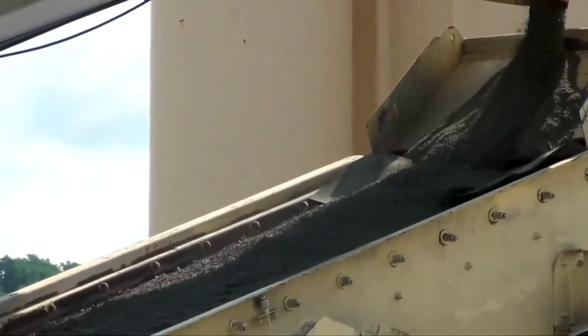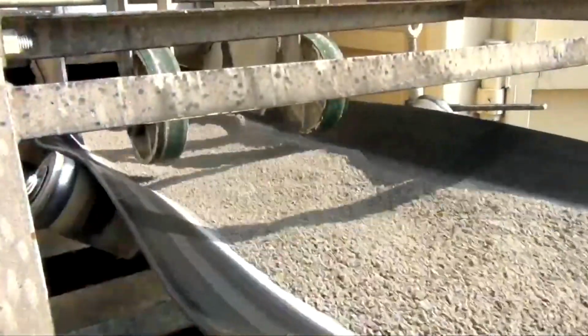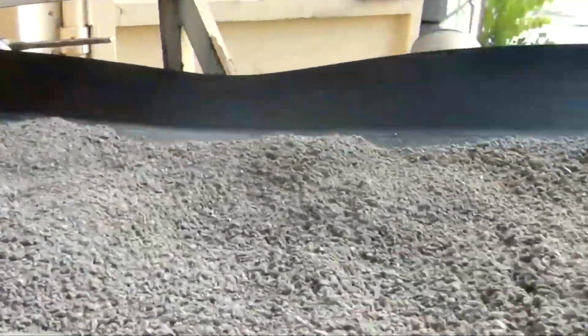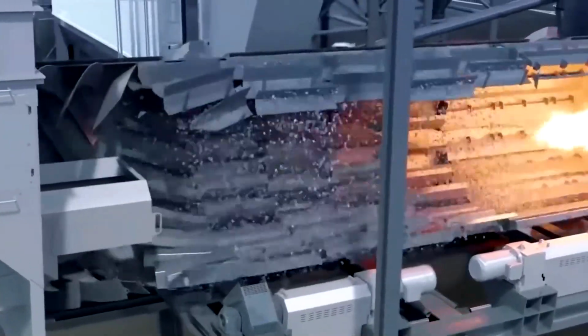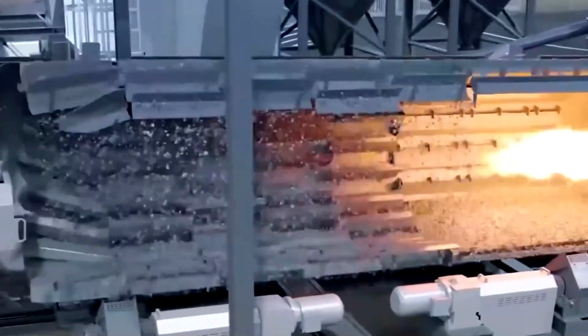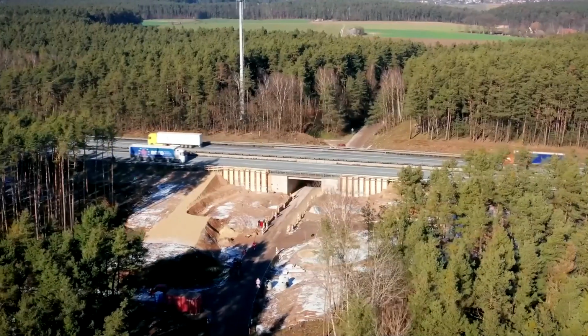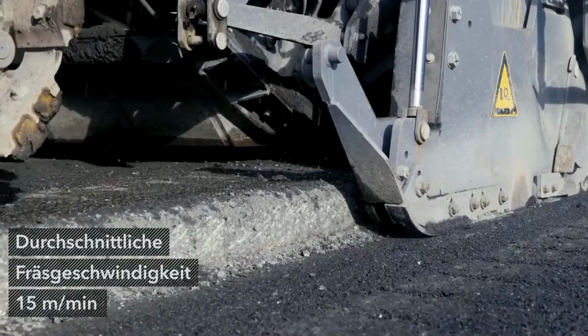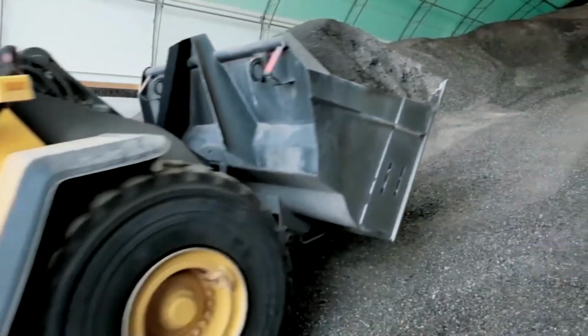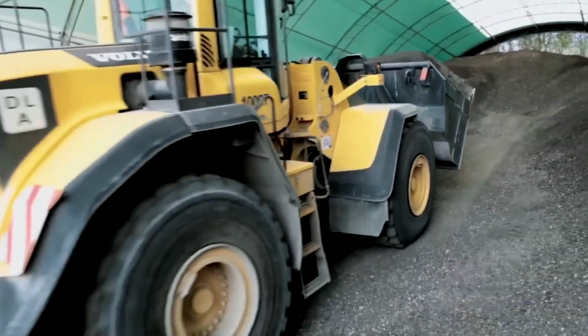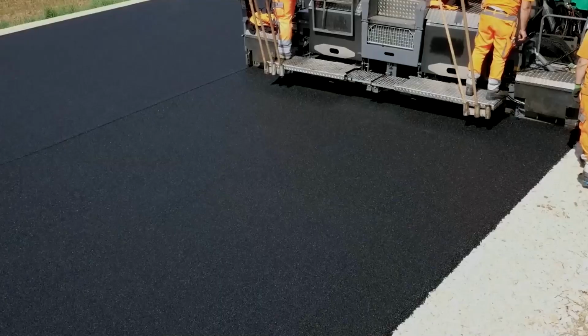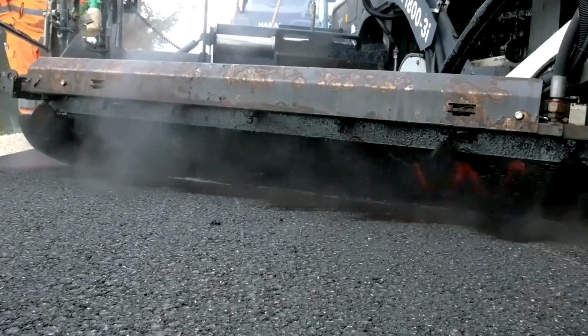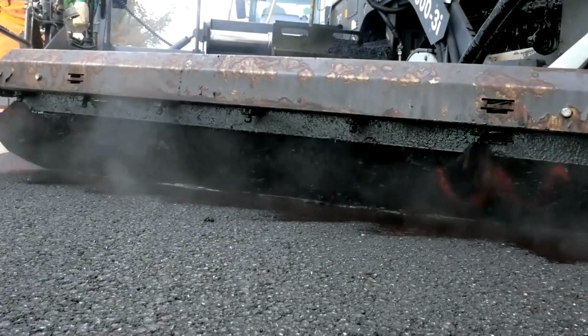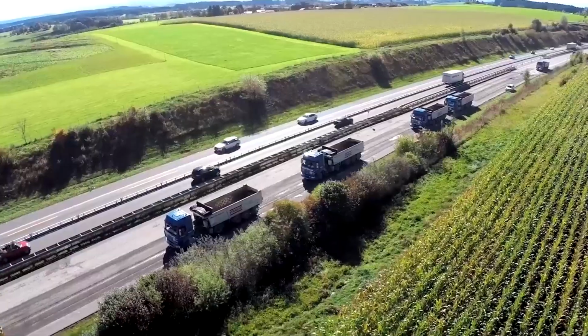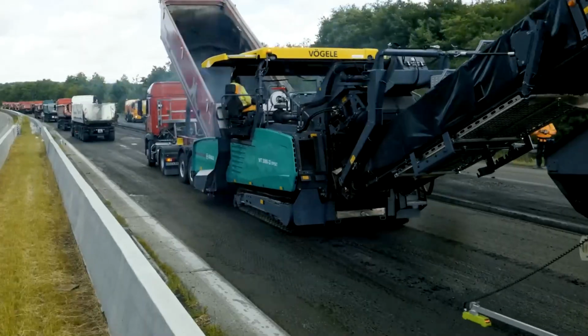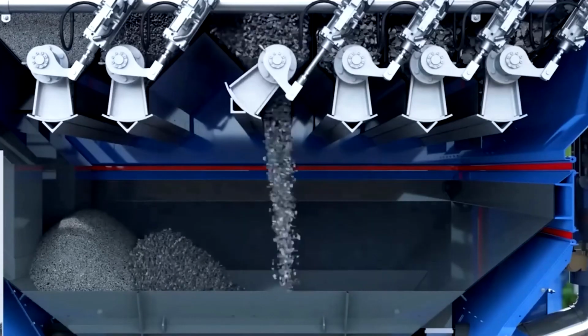It gets more complex further on. The sorted material is mixed with new asphalt binder, fresh aggregates, and a special rejuvenator additive. This chemical agent restores the elasticity of the old binder that is oxidized and has become brittle over time. At the mixing plant, the material heats gradually to avoid burning the aged asphalt components while combining with the hot binder. Modern plants can utilize 30 to 60% reclaimed material in the final blend.